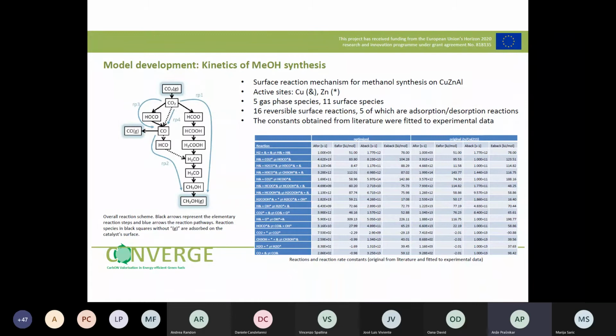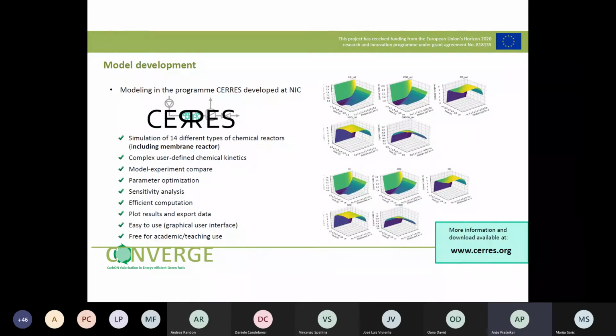So we developed a microkinetic model for copper, zinc, alumina catalysts, which are typical catalysts for methanol synthesis, and it is based on density functional theory calculations. It also takes into account zinc coverage over copper, which are the active sites for methanol synthesis. Solving a large number of equations simultaneously will be performed in CERRES. On the left, you can observe the first results of the developed model. As a result, we obtain concentrations of involved species in dependence of time and axial dispersion for retentate and permeate side.